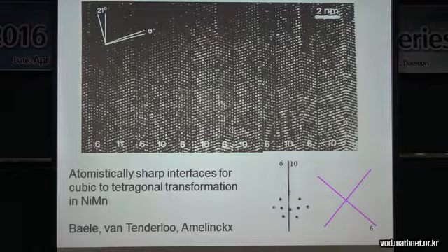Okay, so now the cubic axes are into the screen and at 45 degrees to the horizontal. So they're shown here in purple. Now, if you look very carefully at these dots, you'll see that the picture looks like this. So here's one of the interfaces between these layers, and this is a face-centered cubic structure, so there's an atom at each corner and in the middle of each face. To the right is chosen one variant. So it's stretched in this cubic direction, and to the left, it's stretched in this cubic direction.